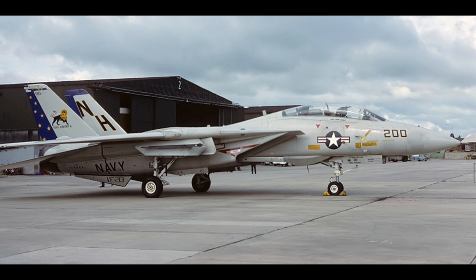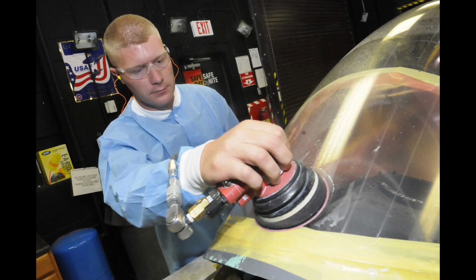Damage tolerance theory, once applied primarily to wings and fuselage skins, was extended to transparent structures. Engineers accepted that cracks would form. The goal was no longer to prevent cracks entirely, but to ensure they could never grow to critical size before detection. To achieve this, redundancy was introduced at the material level. Laminated canopies ensured that even if one layer fractured, others would maintain pressure integrity. Crack arrest layers redistributed stress away from fracture tips. Fail-safe behavior replaced brittle confidence. The canopy became forgiving, not fragile.